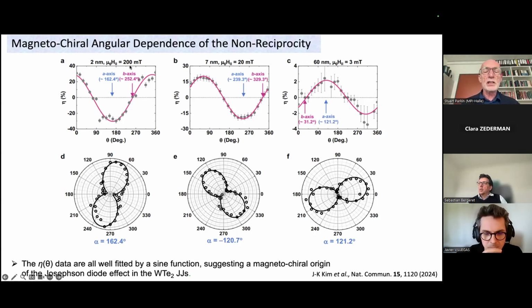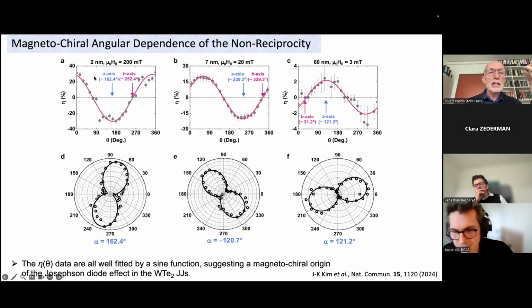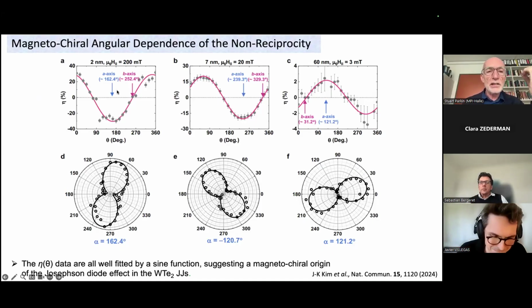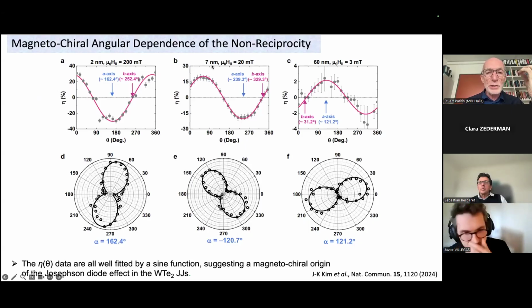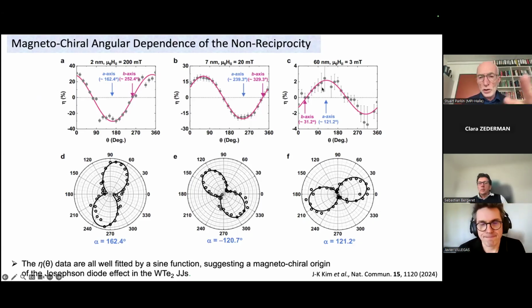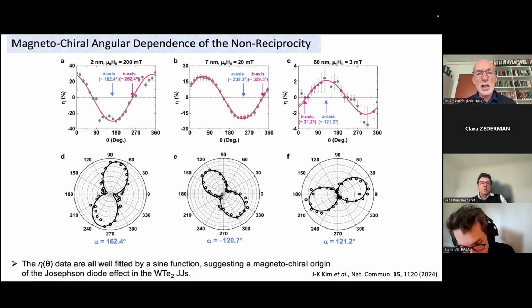On the left-hand side, it's 200 millitesla, and the field is rotated in the plane of the tungsten ditelluride. And on the left-hand side in A, the tungsten ditelluride spacer layer is 2 nanometers thick. In the middle, it's 7 nanometers thick. And on the right-hand side in the C, it's 60 nanometers thick. So in all cases, we see a sinusoidal dependence of the magnitude of the diode efficiency on the direction of the magnetic field in the plane of the tungsten ditelluride.